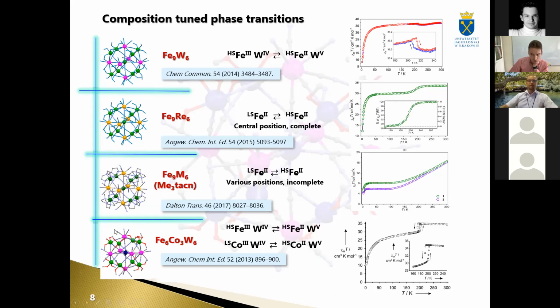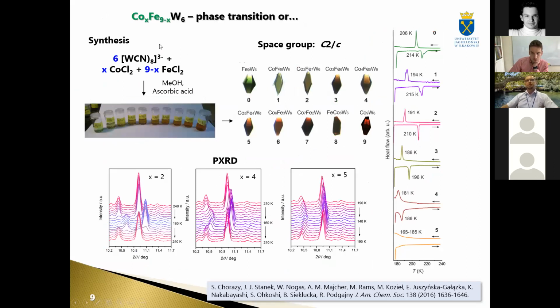So, starting from this trimetallic composition, I would like to present you the first trimetallic composition based on cobalt and iron, which can be exchangeably put into the external and central positions, and 6 tungsten ions. The composition of these phases and of the clusters is governed strongly by the composition in the solutions where they are grown. So this is the iron-rich part and the cobalt-rich part. These are crystals which